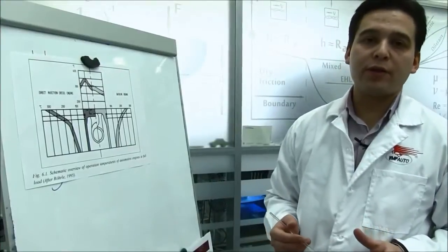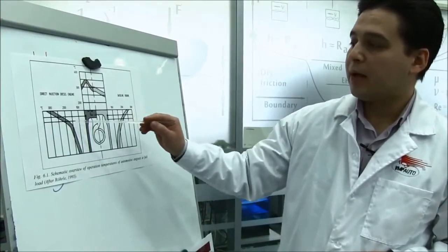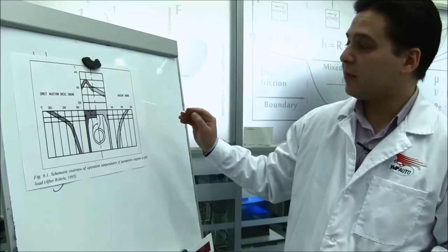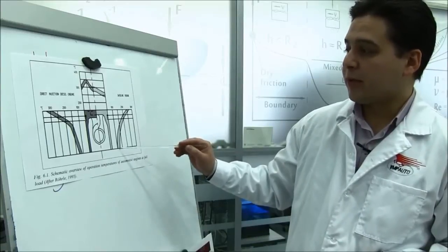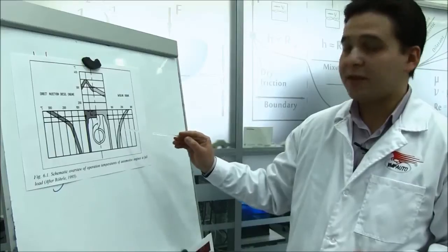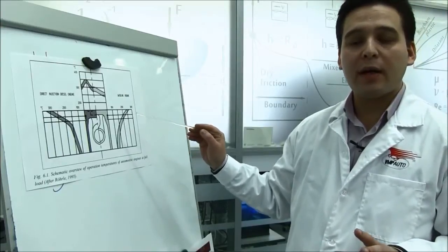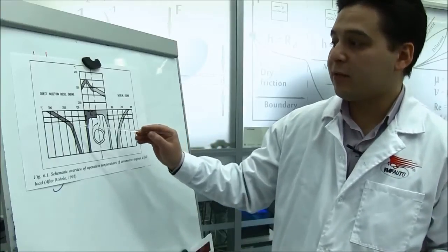Let's take the most heavily loaded friction unit in the engine, a cylinder piston group, and take a look at the diagram showing temperatures depending on piston depth. You can see that on average the temperature in the lowest point is about 100 degrees, and in the highest approximately 250 degrees for the petrol engine. The medium temperature for the HTHS viscosity will be 150 degrees centigrade.